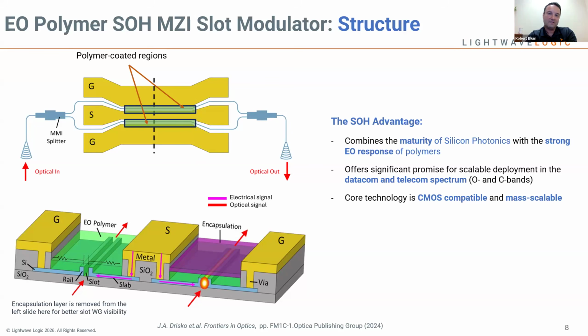So in essence, you etch a slot into your silicon modulator, and then you backfill it with polymer, so that you end up with a hybrid mode where the mode is in the silicon and in the polymer, and you're essentially only limited by the RC constant here. And so you're making these Mach-Zehnder modulators as an example, even though you can make ring modulators as well. But for these Mach-Zehnder modulators, you basically have two arms that are both filled with polymer.